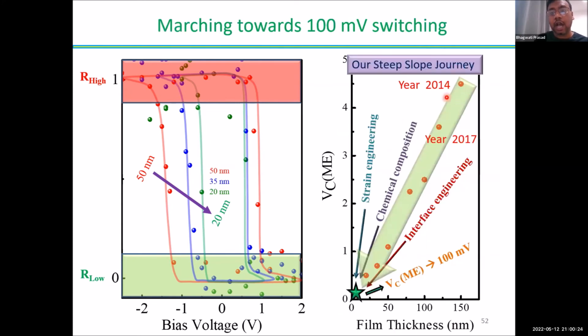Okay, so this is how our journey was: we started in 2014, then in 2017 the switching voltage was around 3.5 volts, and we have achieved all the way down to 500 millivolt, and the aim is 100 millivolt. We did demonstrate something close to 100 millivolt, but we could not get really nice working devices with that, but up to 500 millivolt, we have nice working devices.